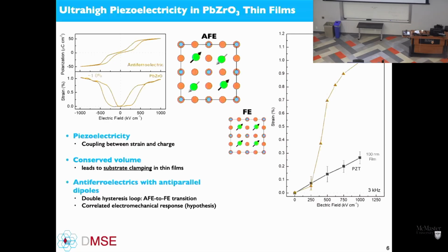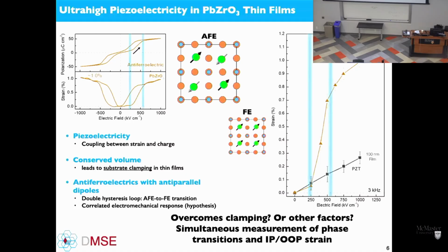If you go to an antiferroelectric, now you can, in PZO, get tremendously large strains, much higher than even bulk PZT, at reasonable values of the applied electric field. This is due to the transition between antiferroelectric and ferroelectric within that regime. But what's going on here ultimately is, how does PZO, the lead zirconate crystal structure, overcome that clamping in the antiferroelectric?